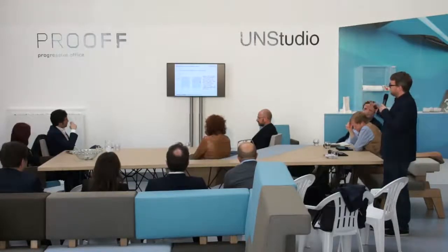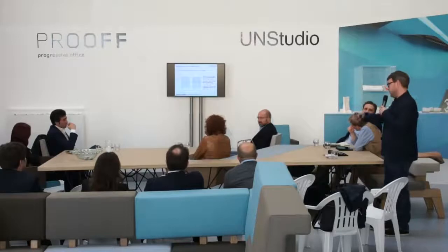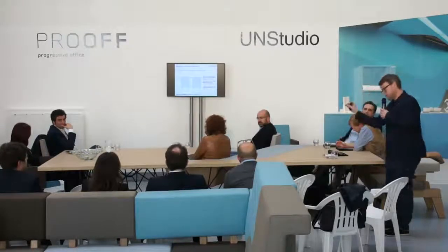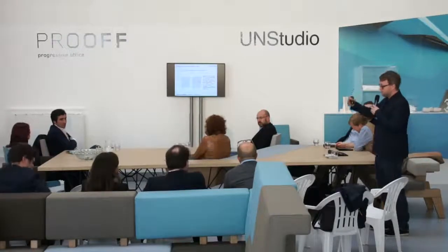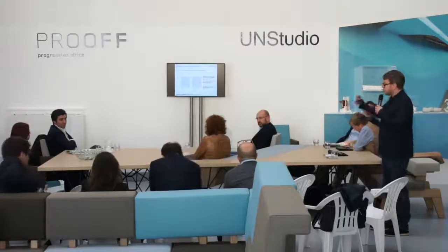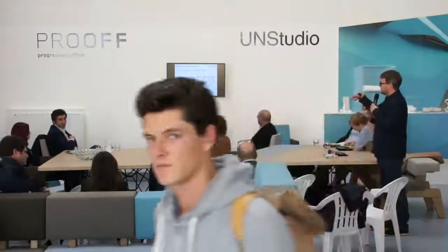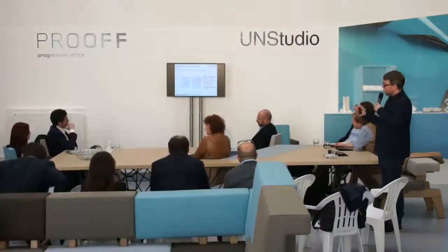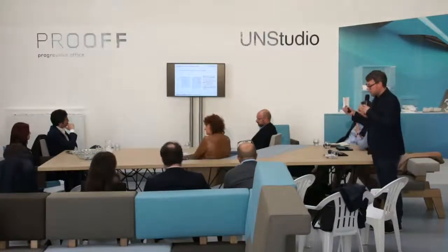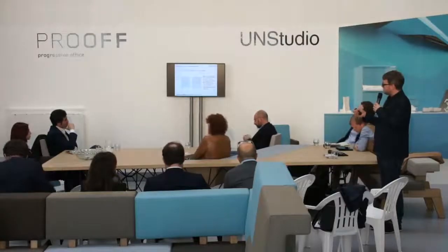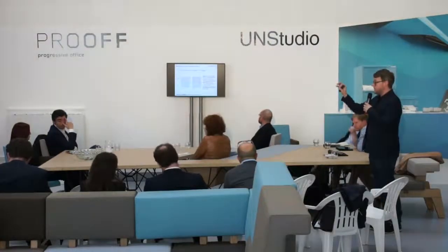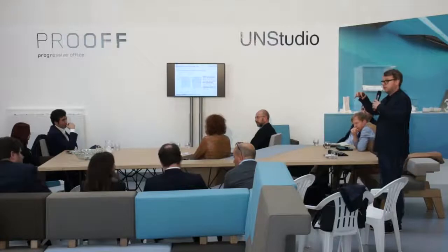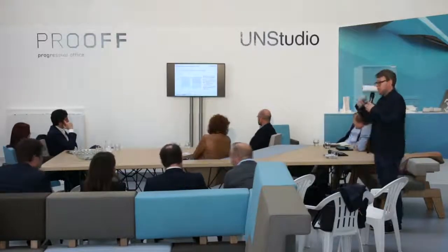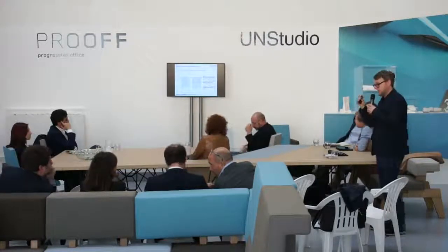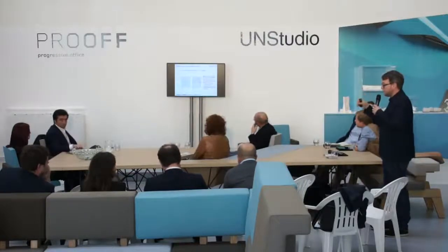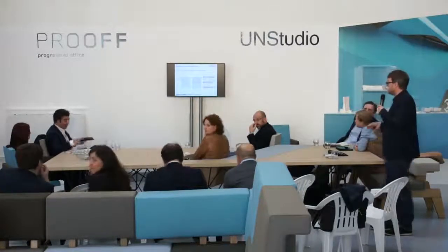But once they take this fusion glass, with the particular product, Gorilla Glass, they take that glass and put it into a chemical bath and chemically temper it, which is an ion exchange process, which allows the ions in the surface of the glass, which are sodium ions, to be replaced with potassium ions in the salts. The potassium ions are much fatter, so they have to crunch together on the surface of the glass, and that crunching together gives the surface of the glass a very high compression, and that high compression gives it the much higher strength it otherwise would not have.